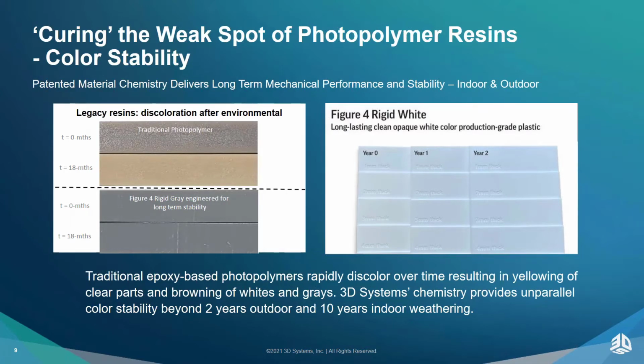With the new Figure 4 photopolymers, specifically the UV stabilized production ready materials, we can take similar materials, in this case Figure 4 Rigid Gray, and after 18 months of accelerated weathering, we can show that we have no visible change in coloring. This is a real game changer when we're talking about stability for materials, because previously any gray material you would see would end up looking brown like we see up here within a few months to a year of outdoor exposure.